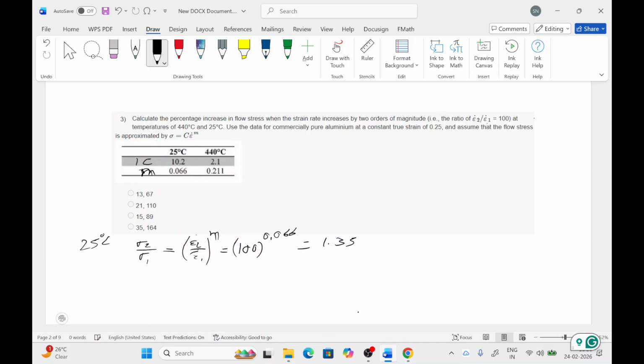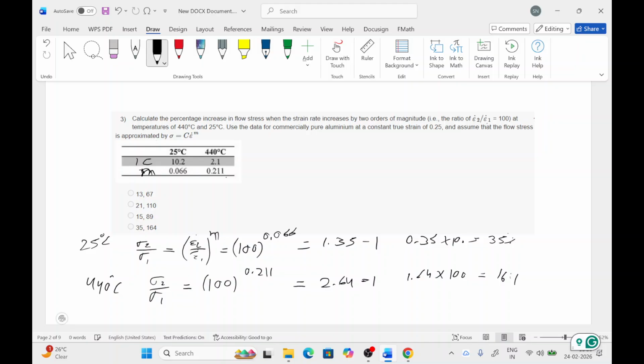So if we subtract 1, it will be 0.35, and if we multiply it by 100, this will be 35%. Similarly, if we calculate for 440 degrees Celsius, this will be 100 raised to power this m value 0.211. So this will be 2.64, and if we subtract 1, this will be 1.64 multiplied by 100, so the change will be 164%.